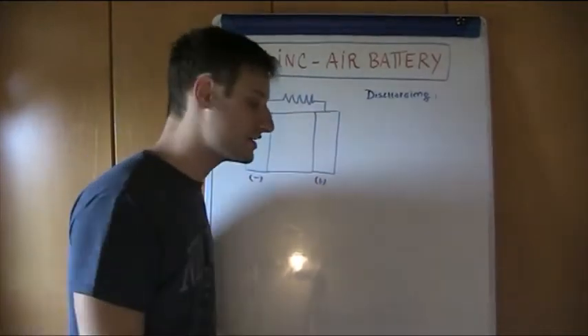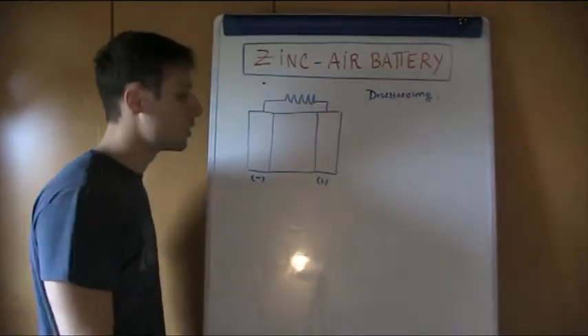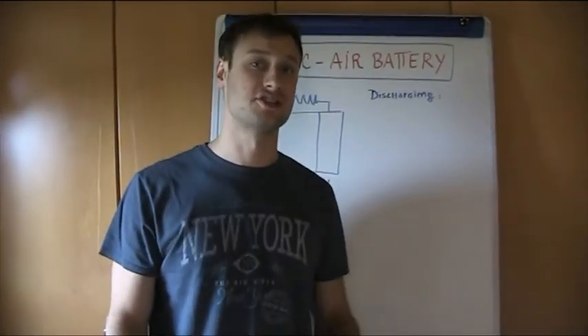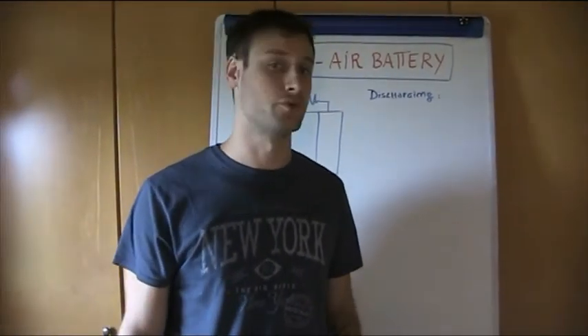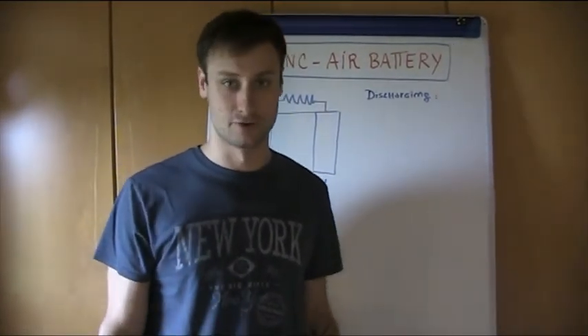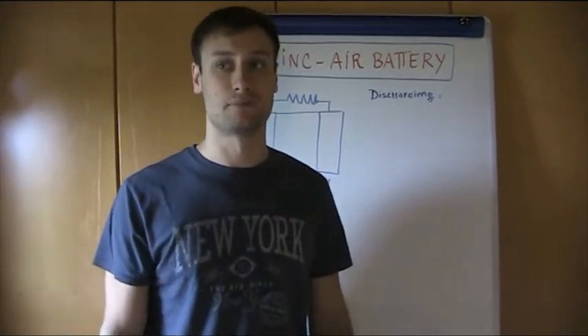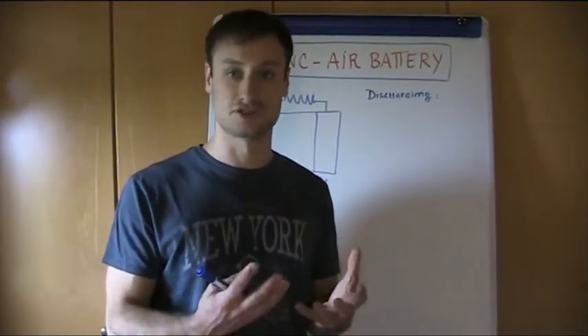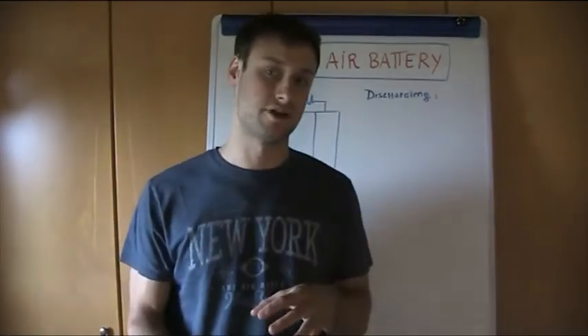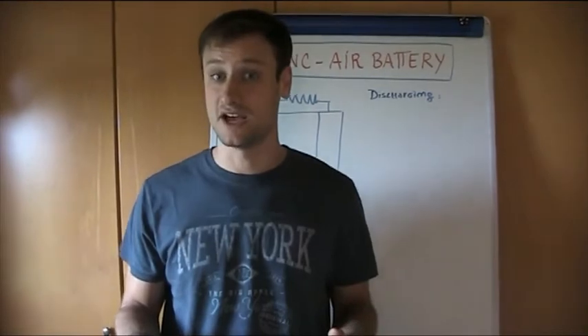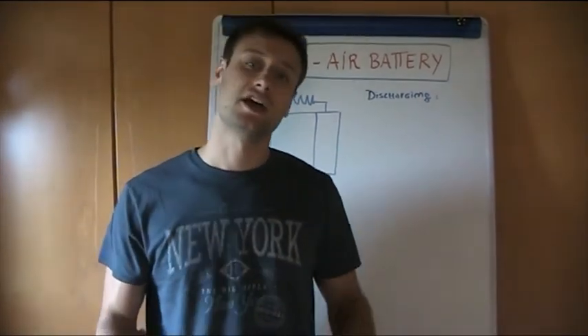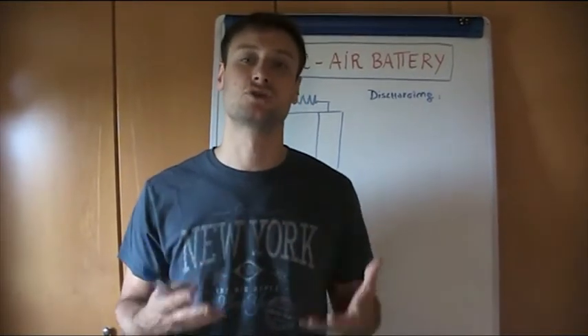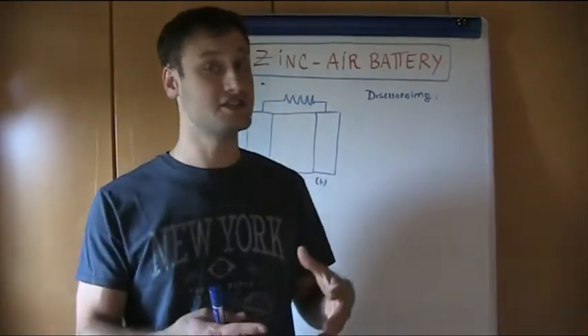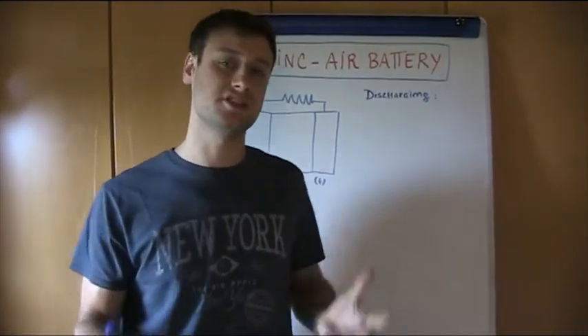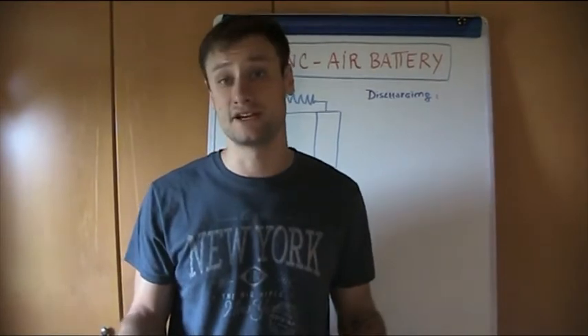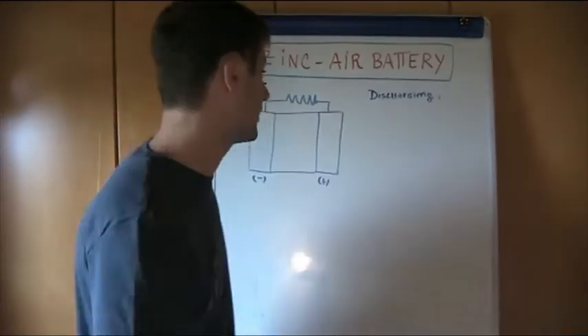Often, in order to maximize the surface area and so increase the efficiency, we use nanoparticles of zinc, particles of zinc in a porous manner. So we especially use a binder, basically in order to ensure the contact between these particles. Obviously, we also need something that is conductive, but in general we use a porous substrate on which zinc particles are deposited in order to maximize the interaction, the connection with the electrolyte. So basically this porous zinc electrode should be completely saturated with the electrolyte solution.